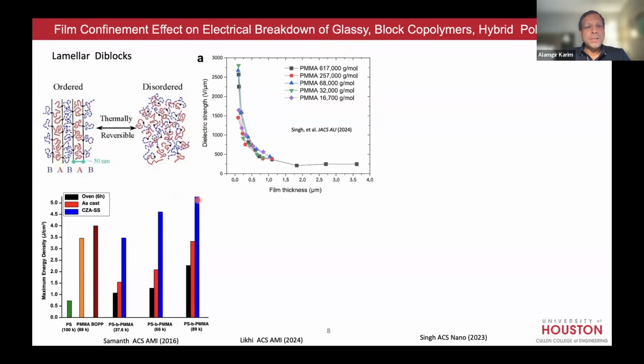But now, remember what I said about interfacial polarization: each block, for example PMMA and PS, has an interface, a dielectric mismatch that contributes to the interfacial polarization. And with it, the energy storage density goes up to almost 5.5 and so on. So that's pretty impressive that just by taking the same material in the disordered state, it's much lower. This really proves that interfacial polarization is a big mechanism for energy storage.